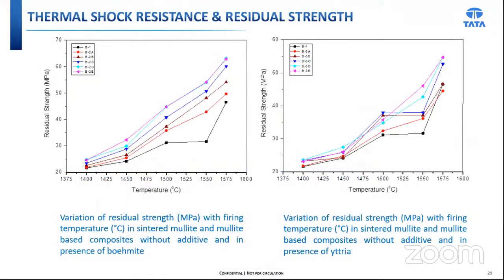Now, the thermal shock resistance result. Basically, all the samples sintered at different temperatures are subjected to 20 cycles of repeated heating and cooling at 1000 degrees centigrade as per the air quenching method. The test result highlights that no microcracks are observed in any of the samples. So, it is proved that it has good thermal shock resistance and greater thermal stability of the sintered mullite compact.